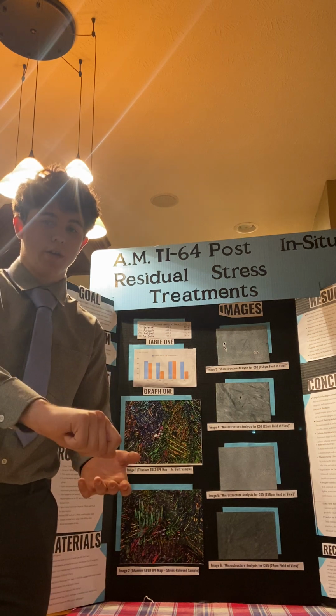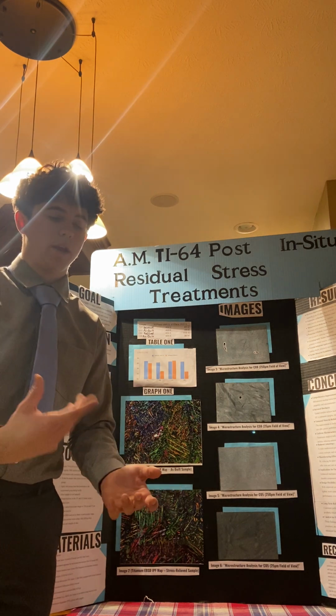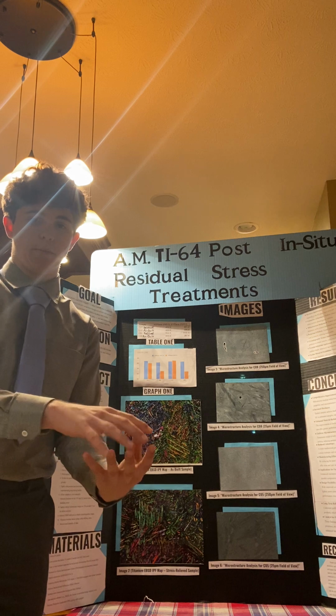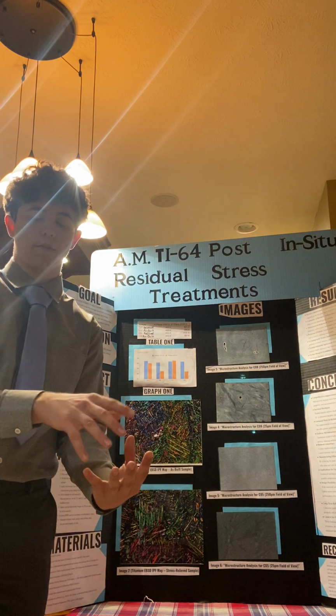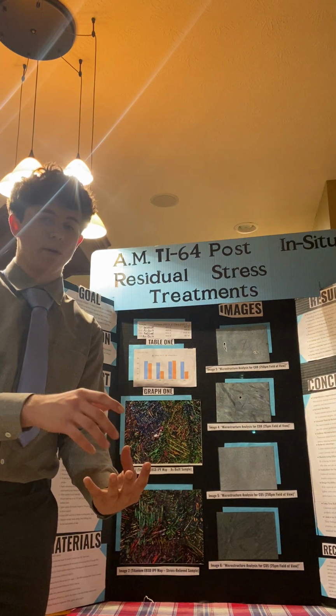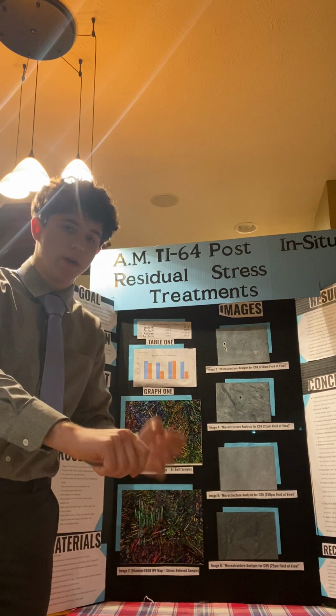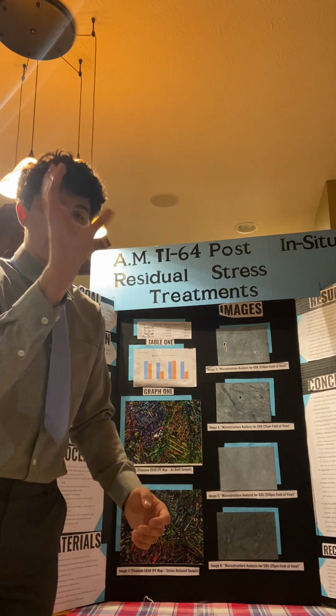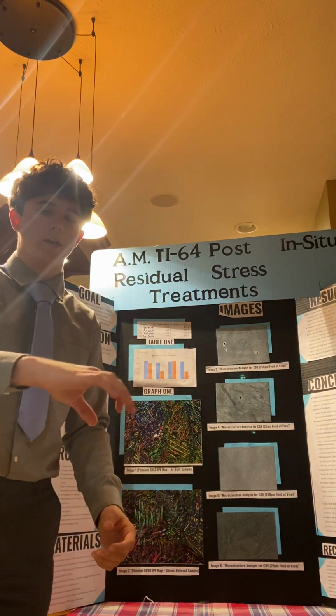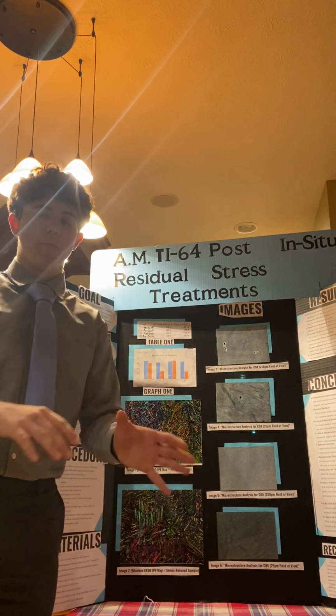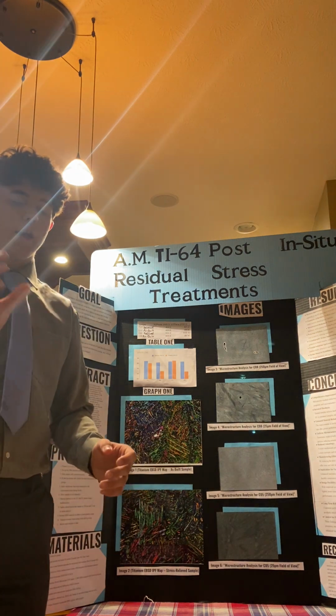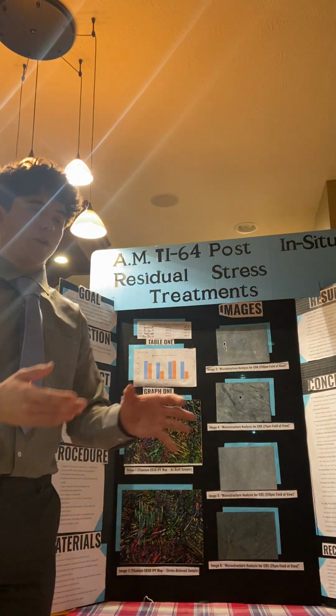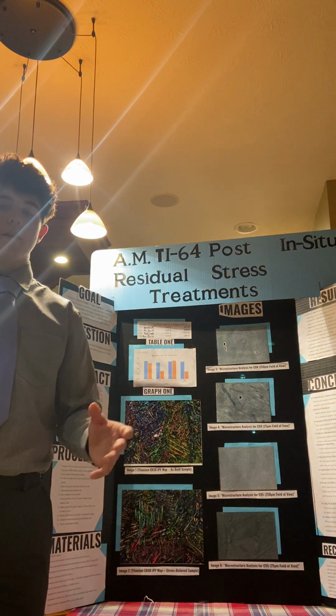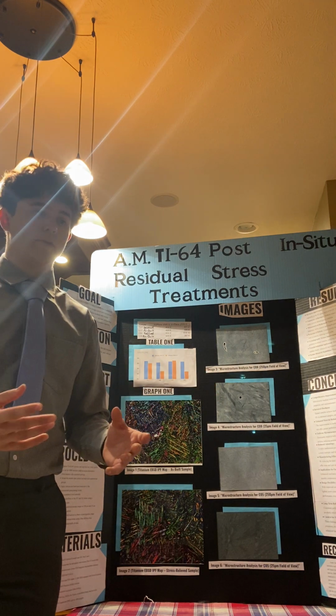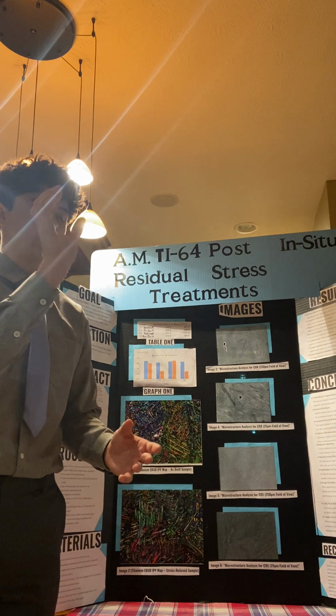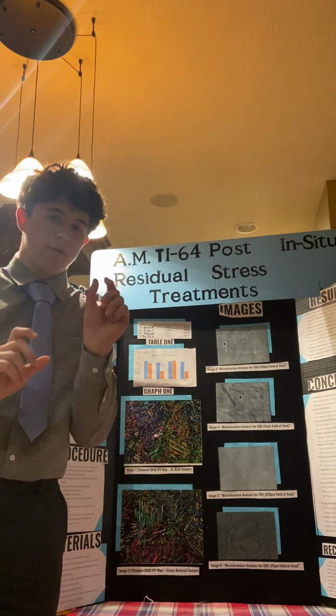And how that works is you're gonna hold it there, and the circle of the plate, basically holding the really rough surface, is rotating at 200 revolutions a minute, and you're going to hold the material to it, and it's going to rotate it, and it's going to create crevices in one direction. You're going to rotate the metal 90 degrees, and then you're gonna go up in the grit level, and as you can imagine, the roughness of the paper is going to get less and less, and you're going to create crevices closer and closer to the material, so that you have very fine crevices.